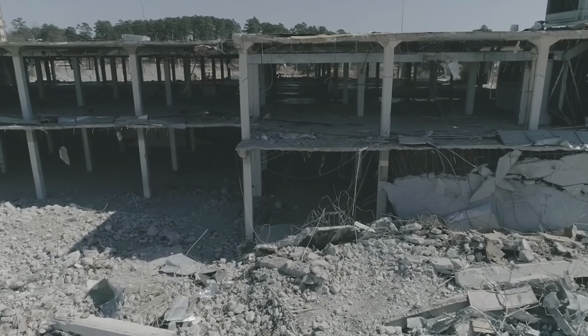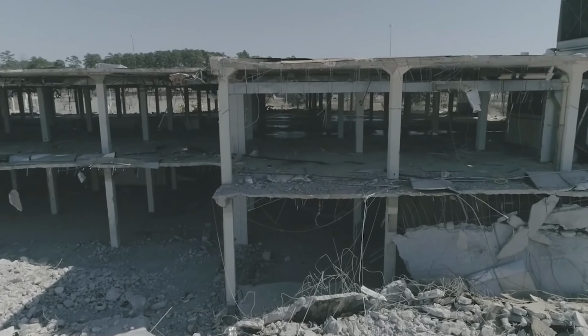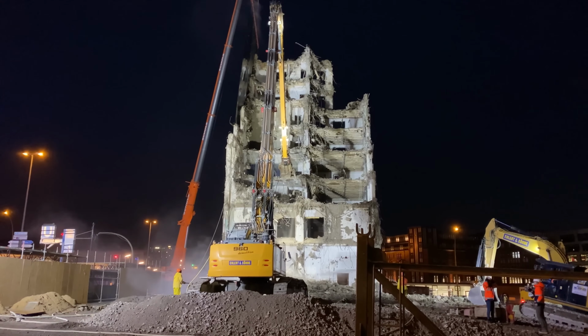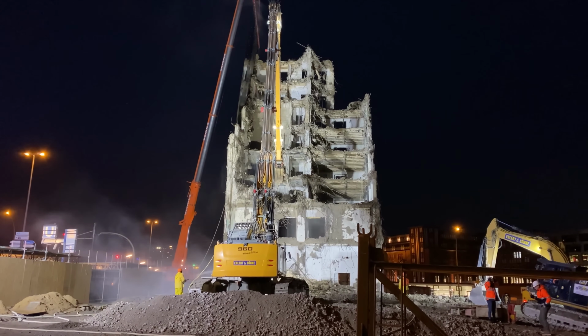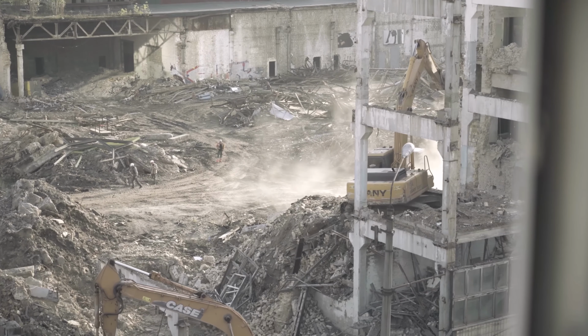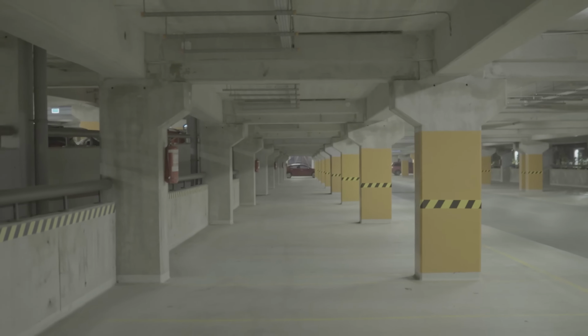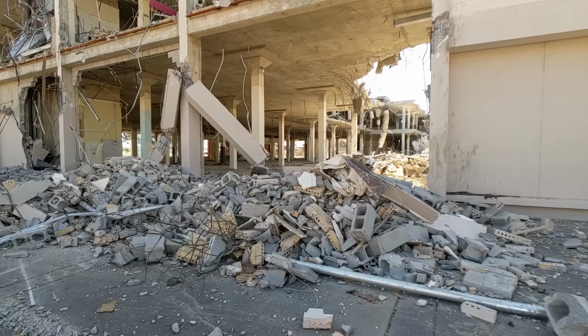But after all, does concrete reach a point where it can no longer be recovered? Unfortunately, yes. When the steel loses much of its cross-sectional area due to corrosion, or when internal cracks reach an advanced level, recovery may become unfeasible. In these cases, it's necessary to reinforce or even replace entire parts of the structure. That's why regular inspections are essential. Concrete may even look solid on the outside, but inside time may be causing damage.